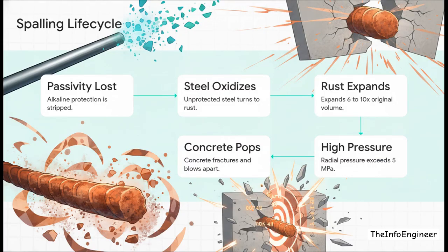So let's walk through the mechanical before and after life cycle of this destruction because it's pretty wild. First, passivity is lost. Second, the unprotected steel oxidizes and turns to rust. Third, and this is the absolute critical mechanical failure here, that rust expands to occupy 6 to 10 times the volume of the original steel. Let that sink in. Fourth, this massive expansion generates internal radial pressure that quickly exceeds 5 megapascals. That's roughly 725 psi, a crushing amount of internal force that just completely overwhelms the concrete's natural tensile strength.